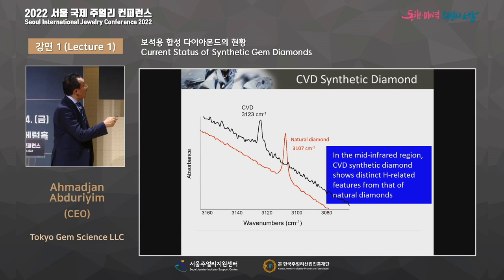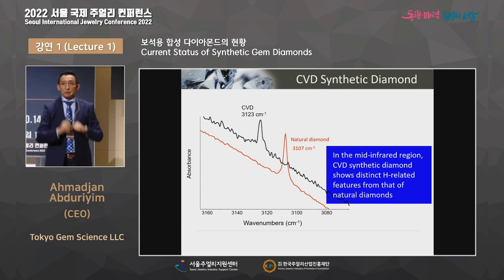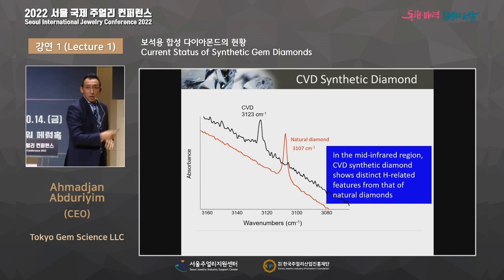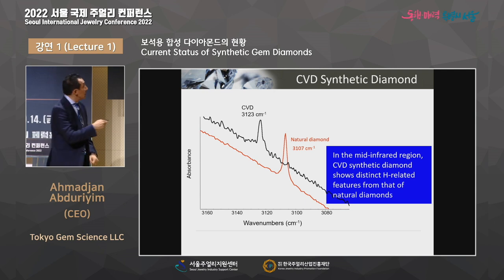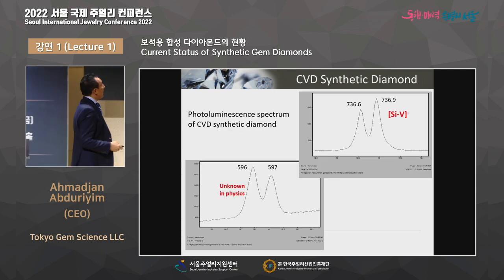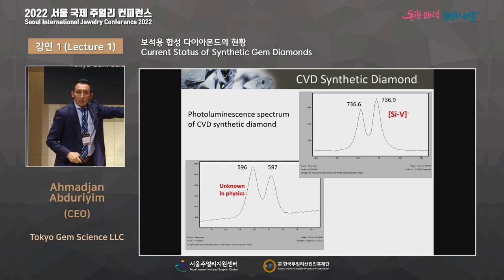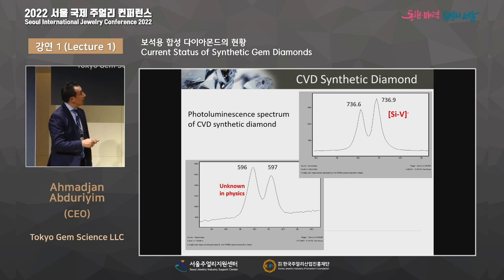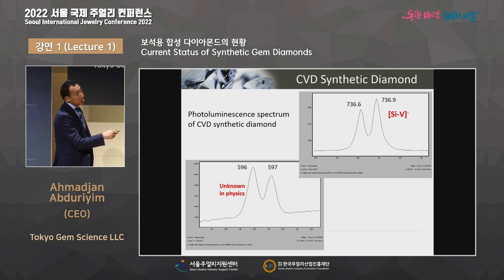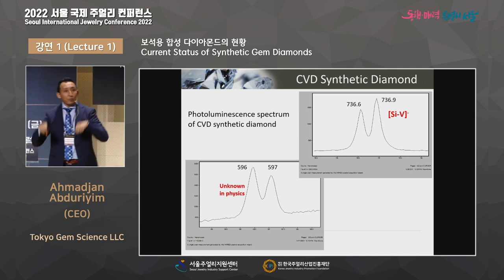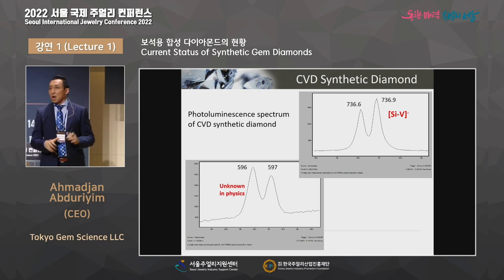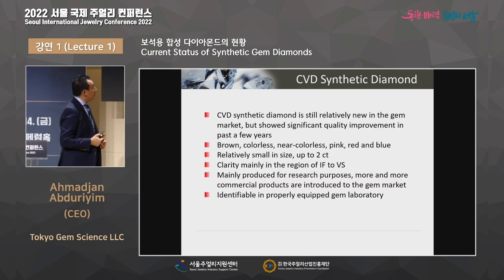So I don't say this is 100%. If you detect this one, lucky, this is a CVD diamond. If without this one, you just have this, you cannot say 100% it is natural. Be careful. After the treatment, this one shifts to here. So this is a problem. And this is 100% proof, by photoluminescence, as I explained. It's near wave number 736. They show the silicon vacancy, negative, with a double peak here. And this one is an unknown defect near 596. They show these two double peaks. So on your photoluminescence, if you detect these two peaks, it is 100% synthetic. So this will help us a lot.